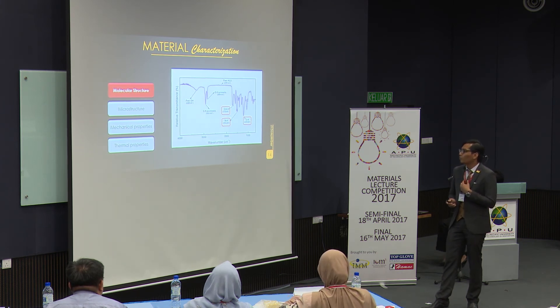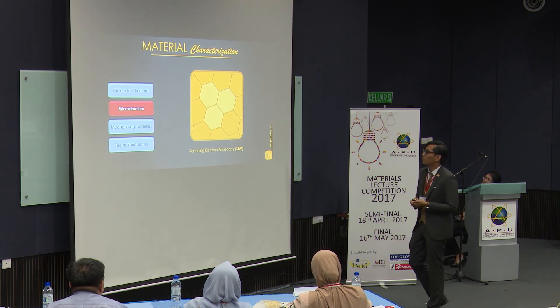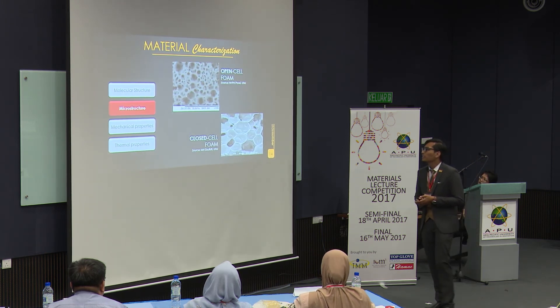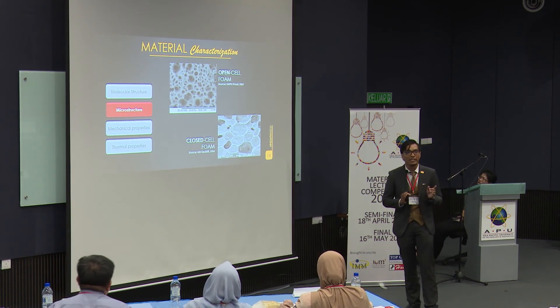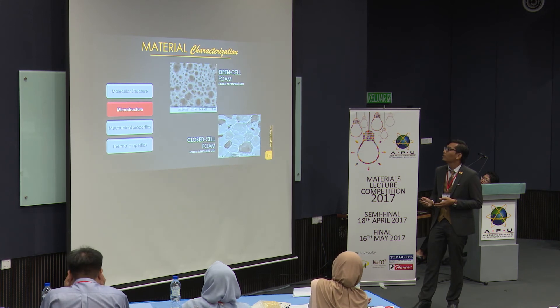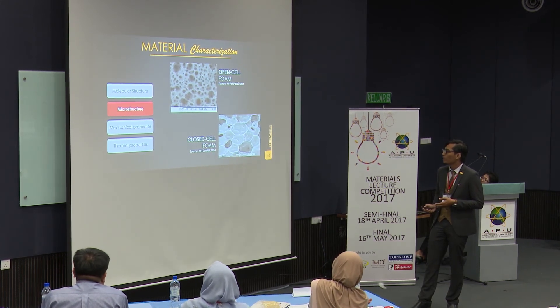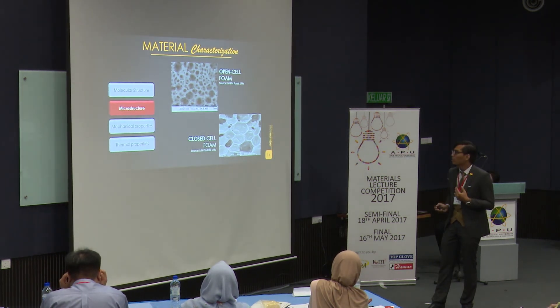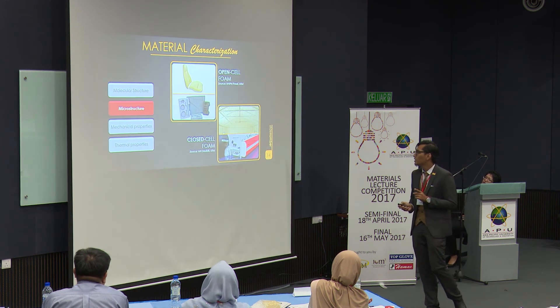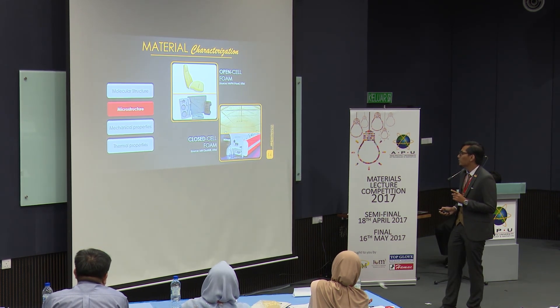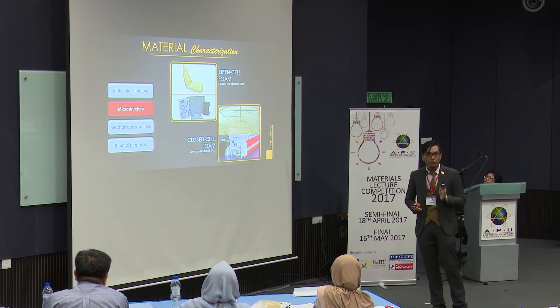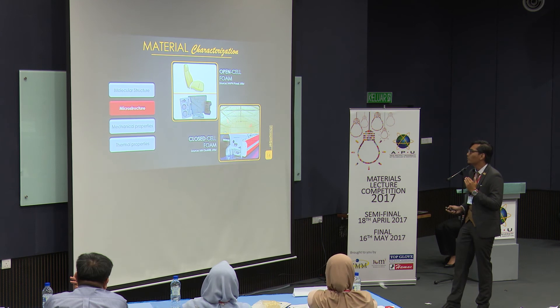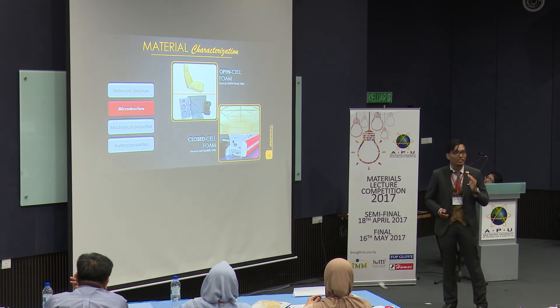The next test is on microstructure, performed using Scanning Electron Microscopy (SEM). The two main distinguishing characteristics observable from this test are whether the foam is open-cell or closed-cell. This also determines the end properties of the foam — for instance, open-cell foam can absorb water but closed-cell foam cannot, which is why closed-cell foam is used in maritime applications. Closed-cell foam also has higher thermal insulating properties, which is why rigid polyurethane foam can be used for insulation purposes.